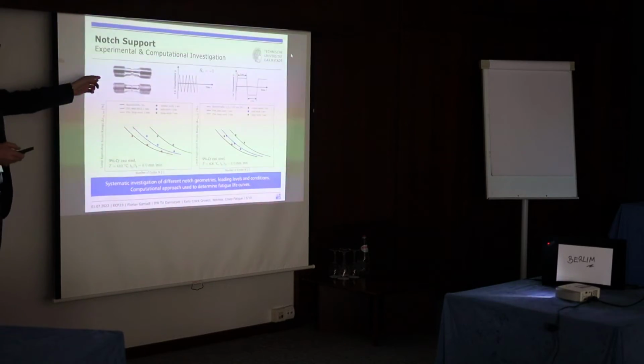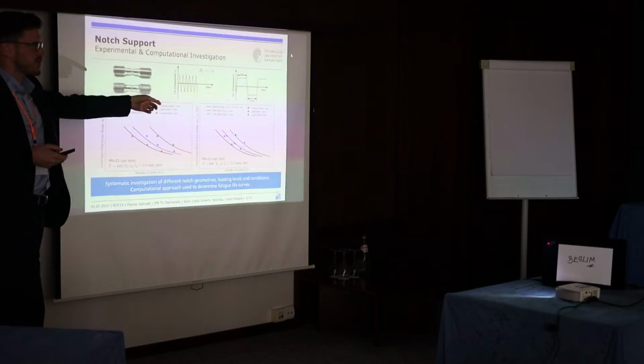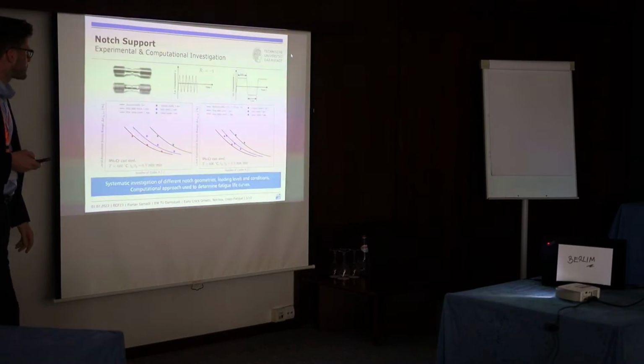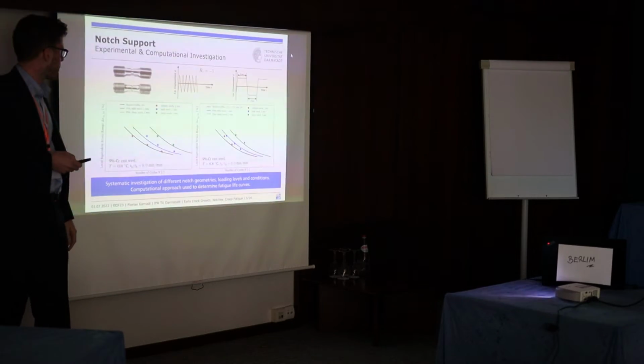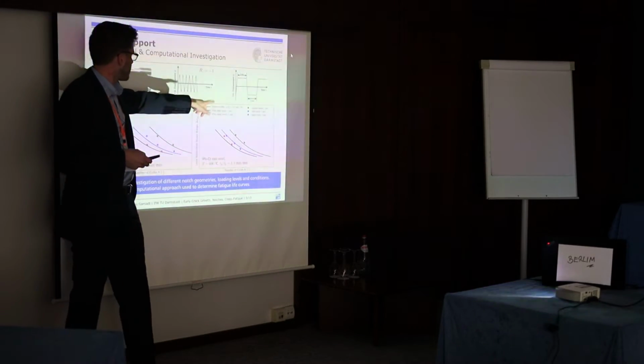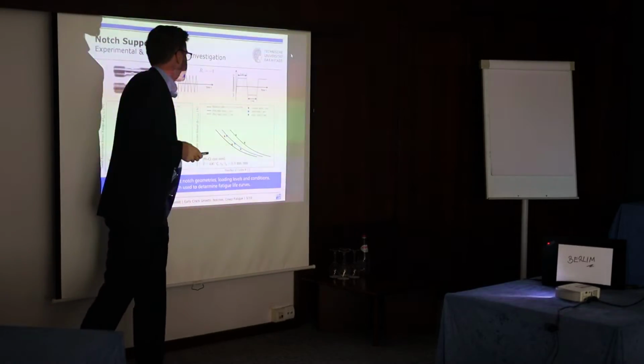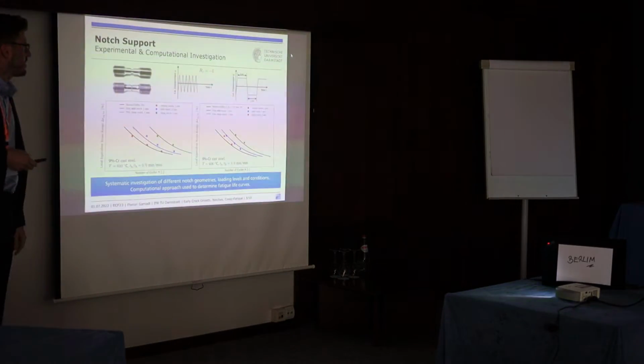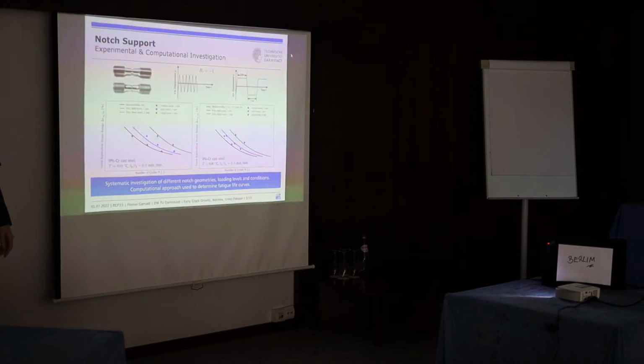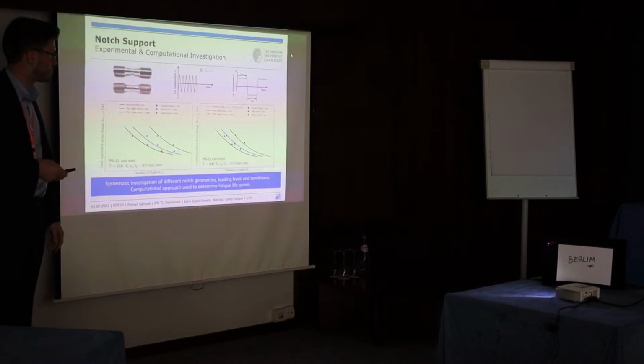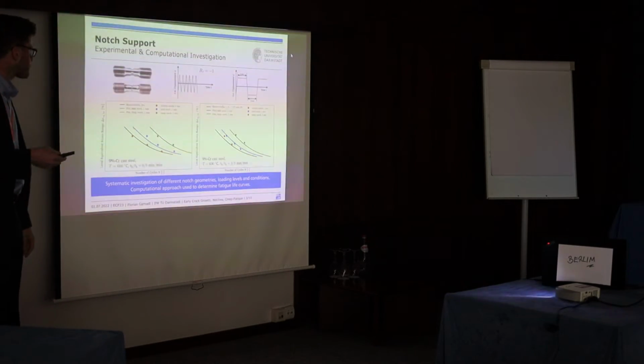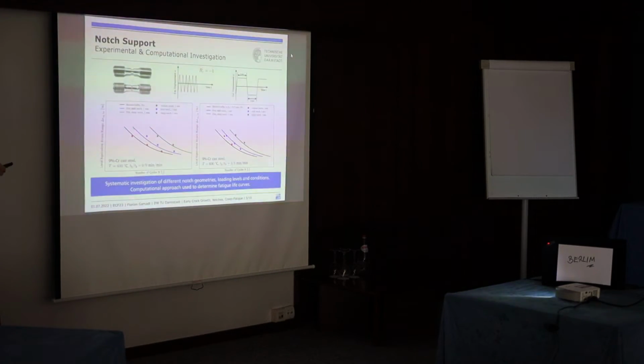We did not just do these tests with one notch geometry, we did it with different notch geometries under different loading conditions. We have a pure fatigue cycle, this triangular shaped cycle here, and we have a trapezoidal cycle with an additional dwell time of 3 minutes in tension and compression to investigate the impact of creep.